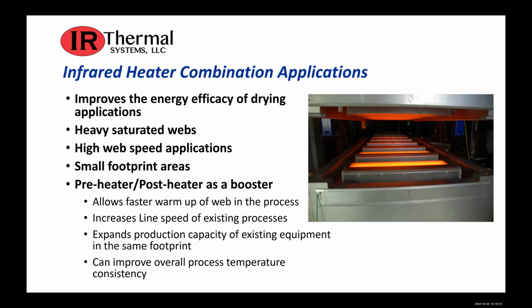The incorporation of IR heating into a traditional convection dryer allows you several things, like it improves the energy efficiency of the overall drying system. It works really well with heavy saturated webs, high-speed applications, or systems where you are required to have a very small footprint. So where high energy input into the web is of the utmost importance. We also use it as preheaters or post heaters for boosters, which allows you to run faster, increase your line speed, which expands your production capacity. And it can also be zoned across the web to improve the overall temperature consistency of your web leaving the drying systems.